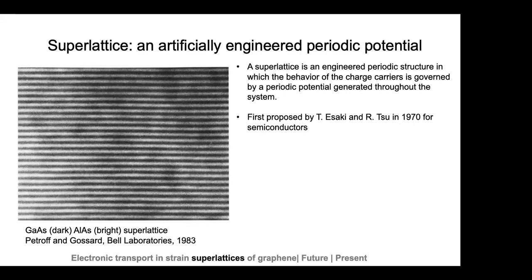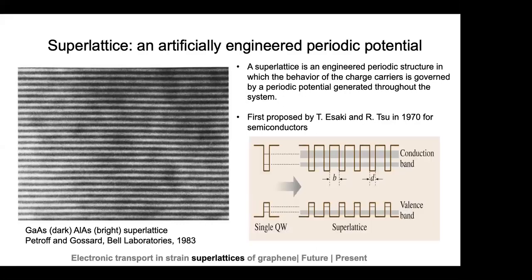So one of the first semiconductor superlattices to be developed in the lab was this gallium arsenide aluminum arsenide superlattice. You have alternating layers of these two semiconductors. These black regions correspond to, can you see my cursor? Yes. Okay, that makes things easier. So these black layers over here correspond to 6 atomic layers of gallium arsenide, and the white ones correspond to 4 atomic layers of aluminum arsenide.